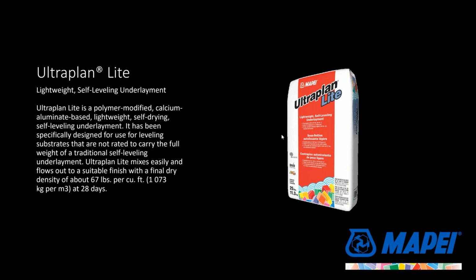So if you're trying to put an awful lot of leveler on a floor, it's adding 12 pounds per square foot additional load. So if you're trying to get 2 inches or even 3 inches of leveler application, that could be an additional 36 pounds, 40 pounds per square foot you're adding to the floor. Now, not all substrates are capable of taking that weight. So we developed Ultraplan Lite, which is roughly half that density. You see 67 pounds per cubic foot. And that will allow you to get to those deep pours. This is suitable up to 2 inches in a single application, and not put so much weight on the floor. So we've done a lot of work with this leveler on cantilevered projects, suspended ceiling materials, where you really can't add that much weight on top of the existing floor. So that's the reason for it.